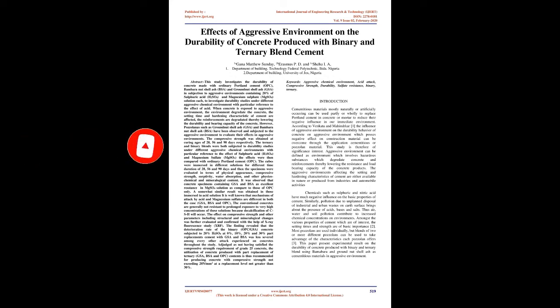It was observed that concrete specimens containing GSA and BSA have excellent resistance in MgSO4 solution as compared to those of OPC only. A somewhat similar result was obtained in those immersed in acid solution.